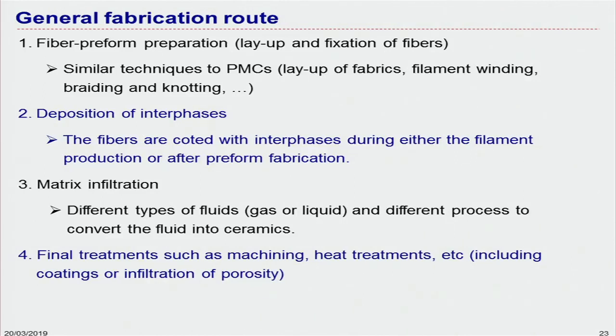Finally, the fourth stage involves machining and heat treatment processes for consolidation or to increase density and minimize porosity. Most CMC processes require heat treatment, mainly because of porosity. By doing these treatments we can reduce porosity from around 30% down to maybe 10%. Traditional techniques such as hot pressing and sintering are good for short fiber techniques.